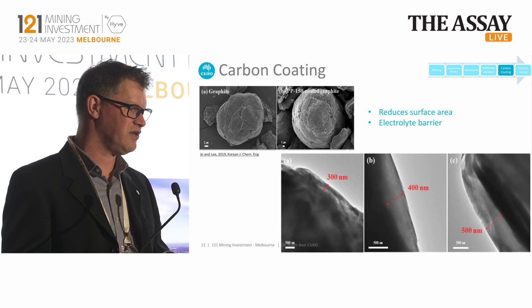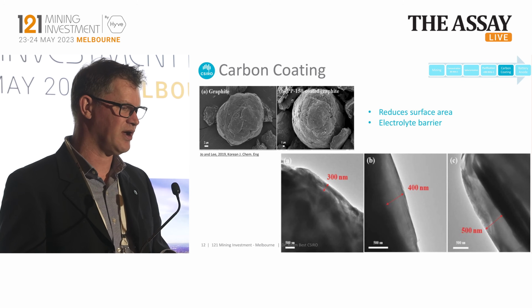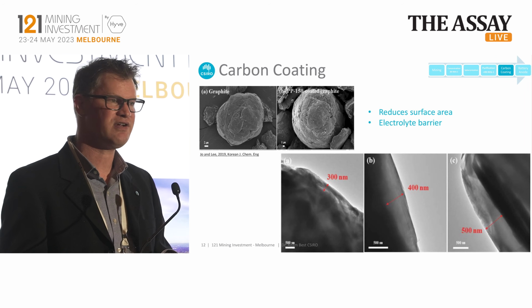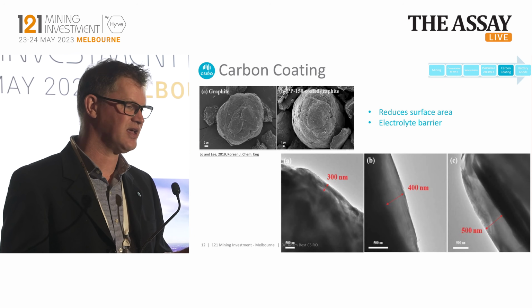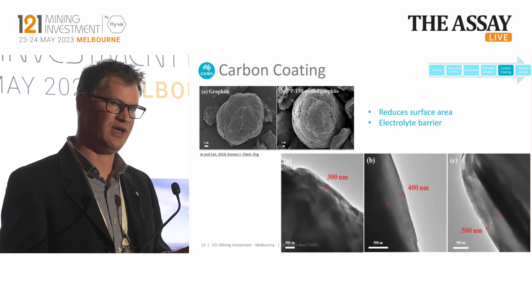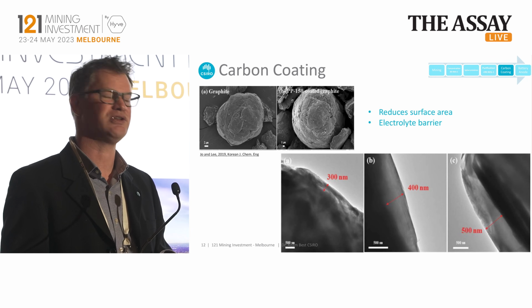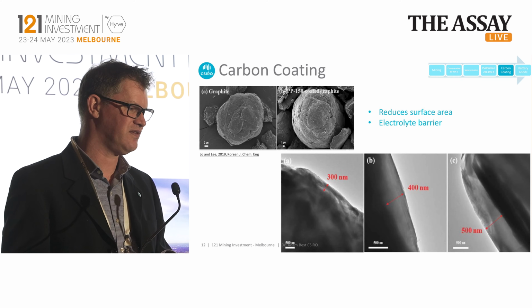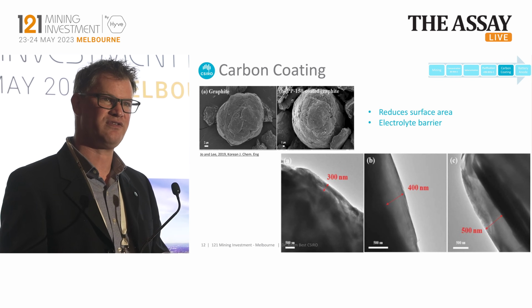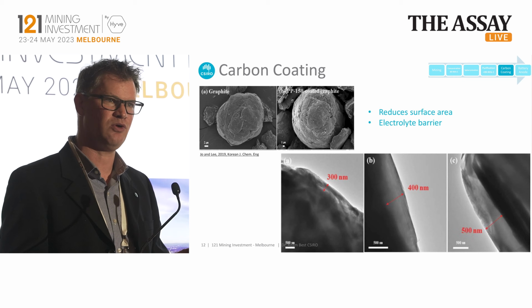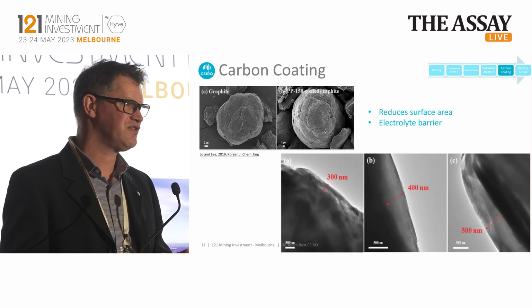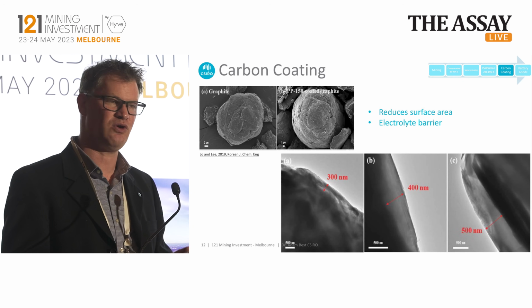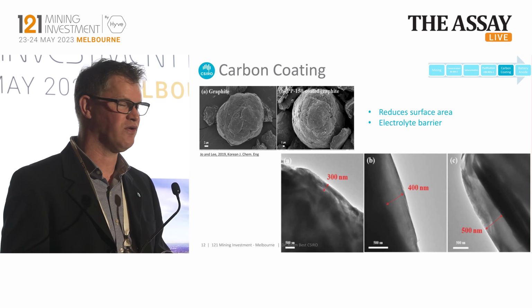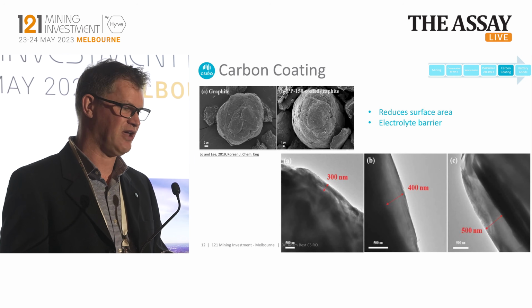And so what you can see here in these micrographs on the bottom right-hand corner is we're trying to get a very, very thin layer of amorphous carbon on that surface. It's transparent to lithium ions, it's electrically conductive, and it will prevent the bulk reduction of the electrolyte on that surface. This is the secret sauce that most battery companies do. They'll normally ask you for the spheronized purified material, and then they'll normally put their own special coating on that material before they put it into battery anodes.